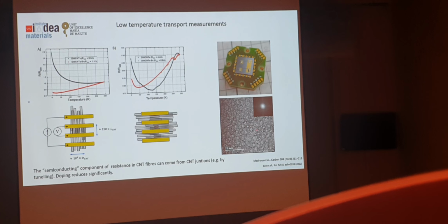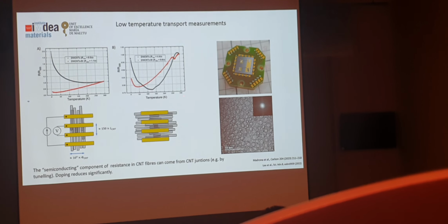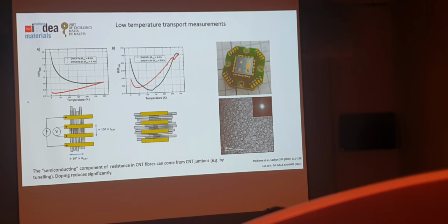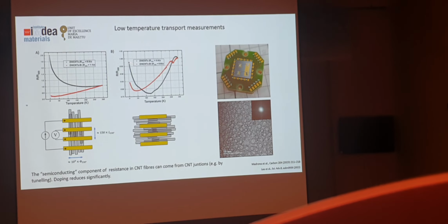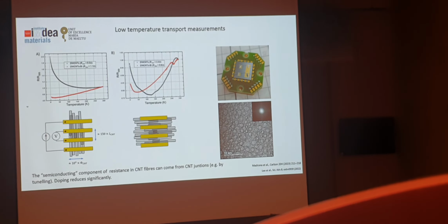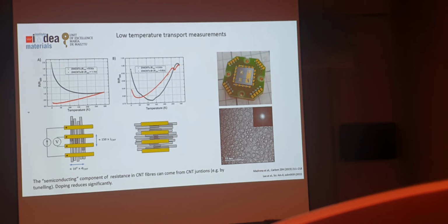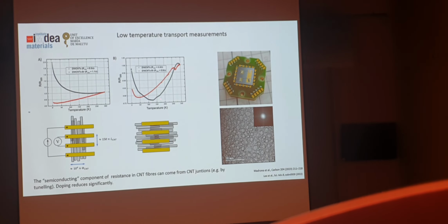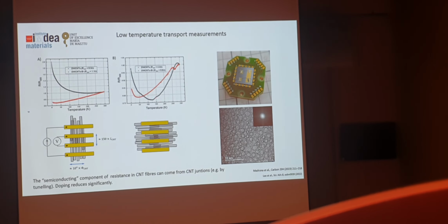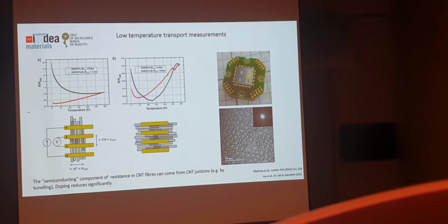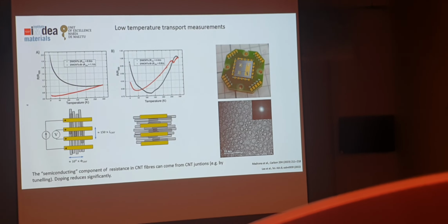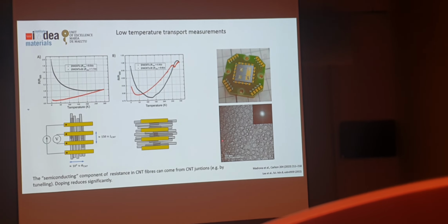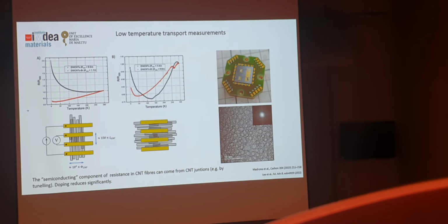there are a lot of these tubes, and a lot of the conduction is probably through the junctions between them. So to test this hypothesis, we measured the transverse conductivity, and sure enough, the transverse conductivity also increases hugely after doping. So I guess what I'm saying is we need better models for transport in these large systems. I think they need to include the junctions, which are not, in fluctuation induced tunneling, which is the most common model. You know, that's too simple for this complex system because we need resistances in parallel, not just in series.